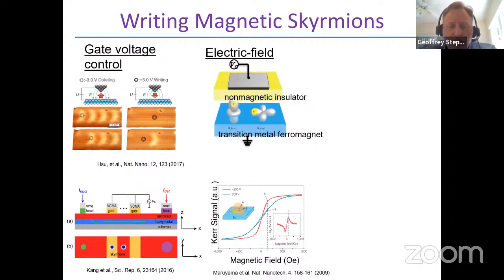Electric fields typically are used to control anisotropy at the interface between a magnetic metal and a non-magnetic insulator, so something like cobalt iron boron adjacent to MgO. And by using either the electric field at that interface or controlling the electron density, it's possible to control the magnetic anisotropy, although the control of that anisotropy is relatively weak typically. So considering the magnitude of the anisotropy that is required for thermal stability of a bit, for example, the change in interface anisotropy using electric fields is only a few percent typically.